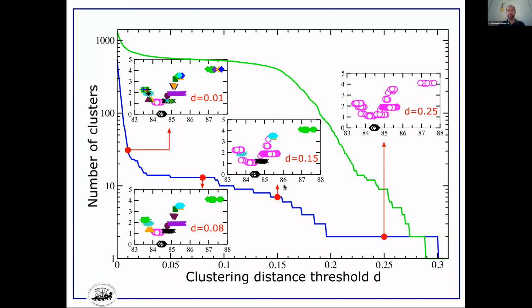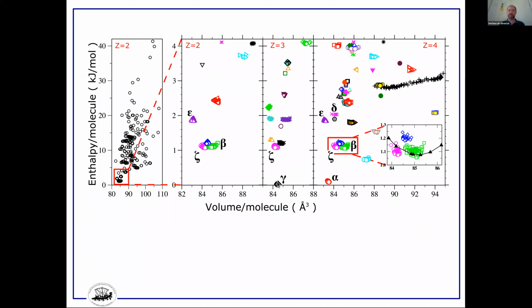The gamma phase, the one which is the most stable, is actually the more diverse, the one that, in a certain sense, departs from the rest of the structure sooner. This is something that we didn't expect, but it is a result that explains why the gamma phase, in spite of being the most stable, is actually not so easy to obtain, because all the other structures that are metastable with respect to the gamma phase are nearer in terms of structural similarity. And so the gamma phase, which is the most stable in our calculation and in reality, is somehow isolated in the structural landscape.